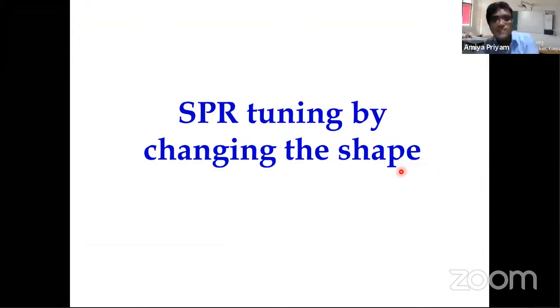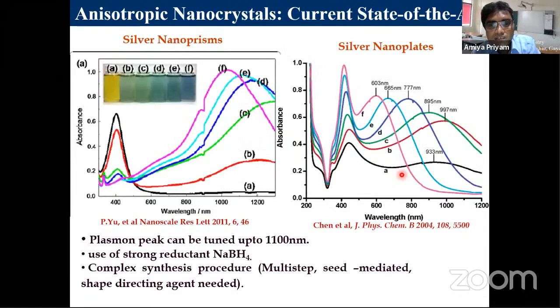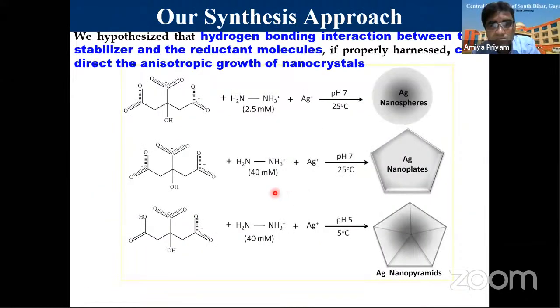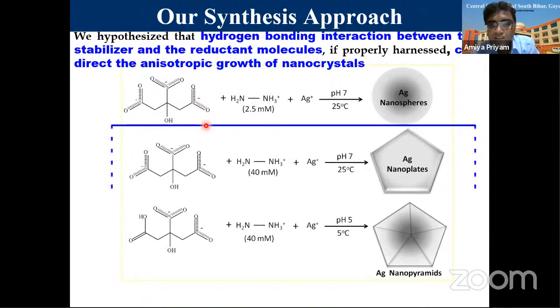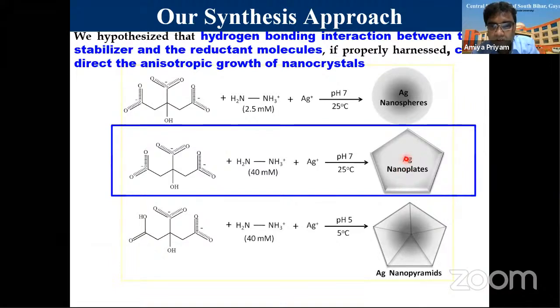Okay. So these were the hollow nanoshells, and I talked about how by changing the structure we have been able to tune it to the near IR region. We also were able to tune the plasmon peaks by changing the shape, and this is our method that was developed, which was a seedless method. Most of the previous methods used seed nanoparticles and then grew an anisotropic structure. Here it is a single step process, direct synthesis, which involved the tuning of hydrogen bonding interaction between reducing agent and the capping agent. By this way, we were able to form spherical nanoparticles, nanoplates, nanopyramids.